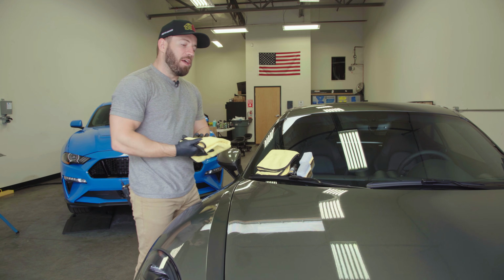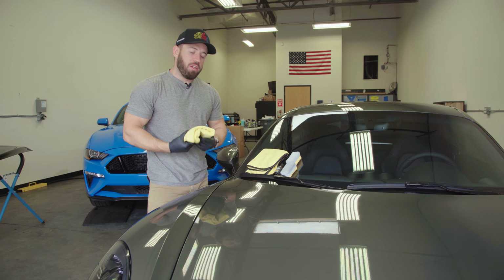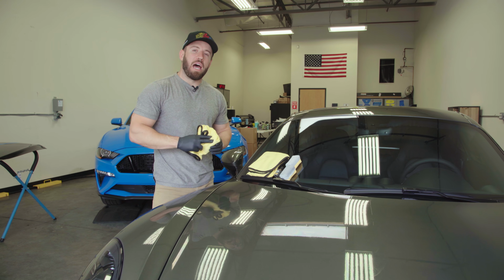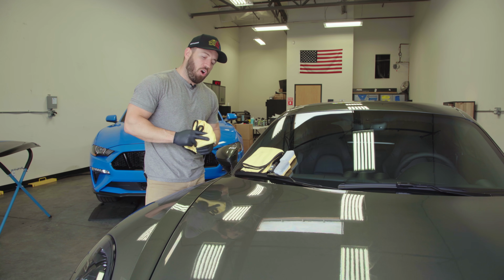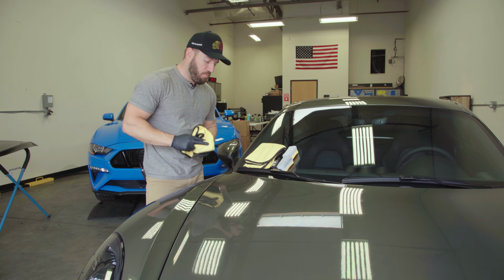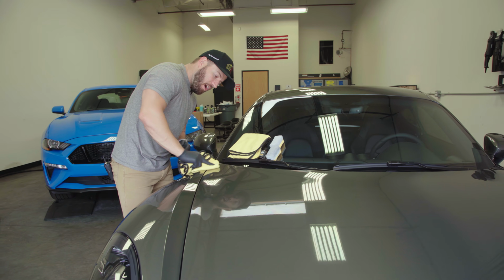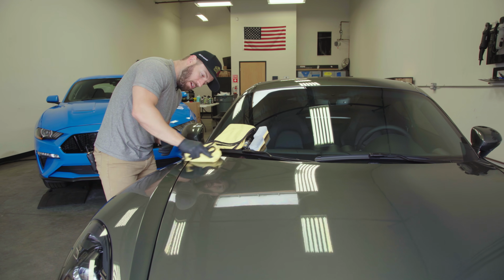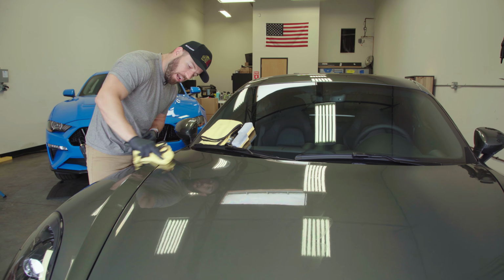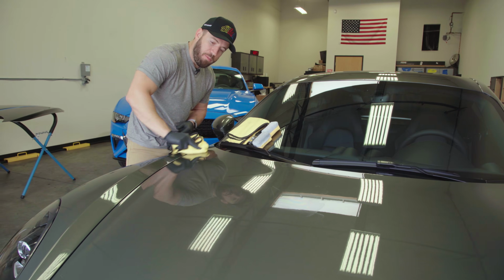Now that it's been about a minute, it's getting close to wiping off the coating. So I'm going to do a little test spot with my towel first to make sure that the coating is ready for removal. Now I'm going to do quite a small little circle here just to feel the coating. Now a lot of this can be done by eyesight. Like I said, the rainbow starts dying down, it starts hazing. But a lot of the wipe off in terms of whether the coating is ready or not can be done by feel too. If the coating feels very firm or grabby, you waited a little bit too long.